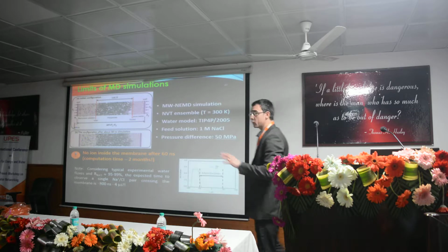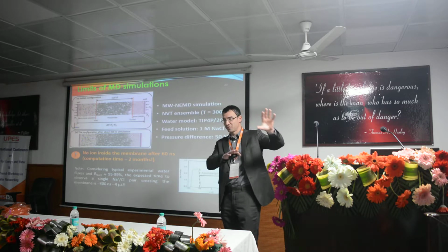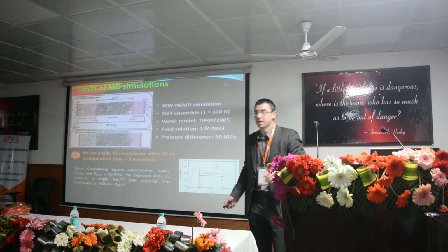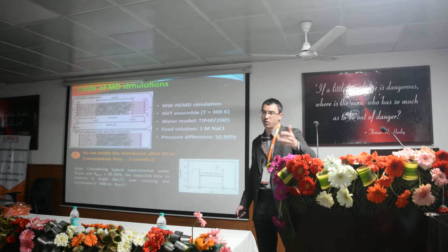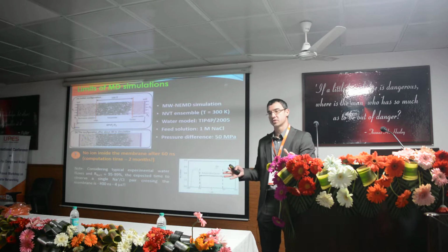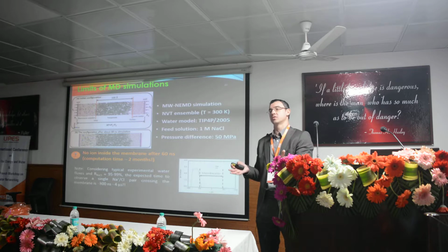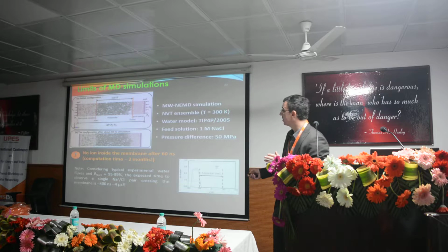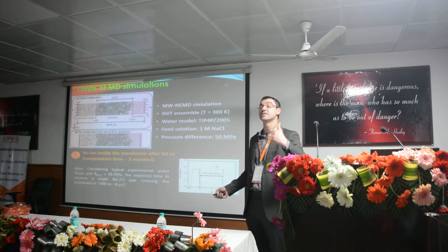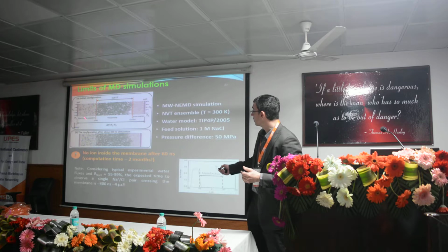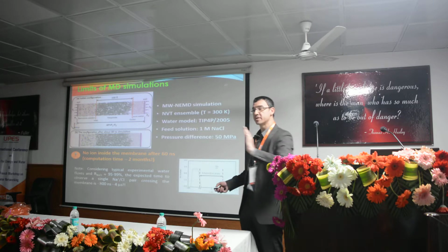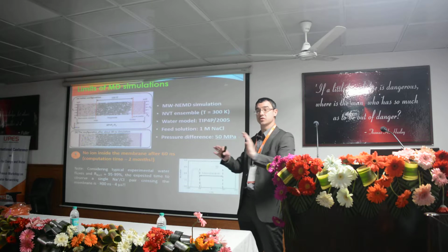Well, that was for the good points of molecular simulations, but we must admit that these tools have also their limits, of course, and the limits are, as I said before, related to the computational resource. In other words, the simulation times are very, very limited. In this example, we were interested in investigating the desalination of seawater. So we considered a sodium chloride solution, added walls onto the system on both ends, and used these walls as pistons, just to simulate the real reverse osmosis process.